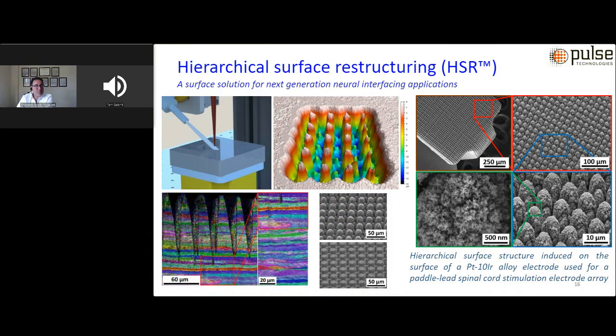So thickness of the electrode is really important, because the process essentially is using laser, and the laser spends a good amount of time on the surface of the electrode in order to restructure that surface. And there is also inherently some degree of material ablation from that surface. And in fact, perhaps I could see if I can bring one of the slides. Can you see this slide now? Yes. Okay, perfect. So that's on the top left. Let me see if I can bring my laser pointer.